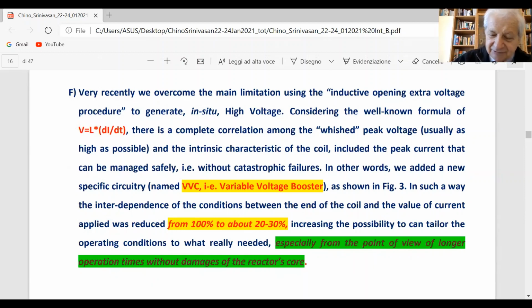The drawback of such a procedure is that the high voltage depends completely on the value of the current injected, the formula being current over time. So if we have a thick wire, we can have a large current, so we can have large voltage. But with a thinner wire, this would be impossible. So we added new circuitry in order to be more flexible, changing the dimension of the wire. We call this one the variable voltage booster.